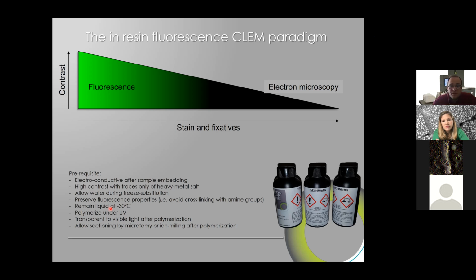Obviously, it should preserve the fluorescence properties. And so we wanted to avoid the cross-linking. So any resin reacting like the epoxy was kind of out of the scope, because epoxy resin reacts with the amine groups of the molecules, and therefore it blocks the fluorescence. This is why EPON is not ideal for preserving fluorescence. It's not ideal. It does not mean it does not allow it. There are some papers around that. Or you would need to remove the EPON after you do the sectioning, which has been published. I've never gone into these protocols personally.